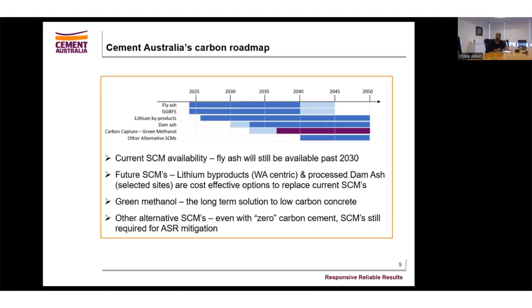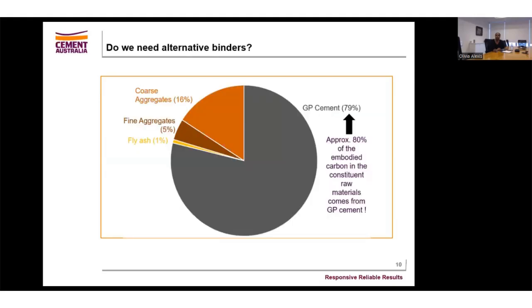But the question still holds, do we need alternative binders? Should we still look at alternative binders? So this is a typical breakdown of a concrete mix. We have GP cement, so general Portland cement. We have coarse and fine aggregates, and we have our conventional SCMs such as fly ash. As you can see in this pie chart, GP cement is approximately 80% of the embodied carbon in the constituent raw materials, which is very significant.